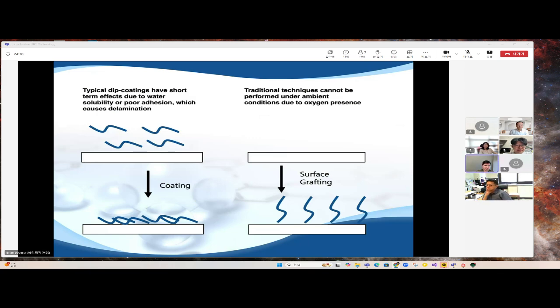The material itself is completely soluble in water, so it dissolves in water. And so if you spray this material onto silicone or some other underlying solid, and you place it in the body, that coating will immediately dissolve away, and so you'll lose your effect, right? The effect will dissolve away with it, and you'll leave behind your bare material.